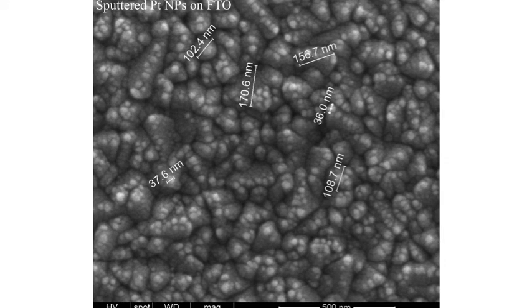Here is a SEM image showing the morphology of platinum nanoparticles on the surface of FTO glass. The small bright points are platinum nanoparticles, and the rough surface background is FTO.